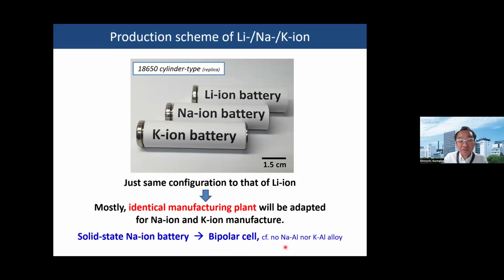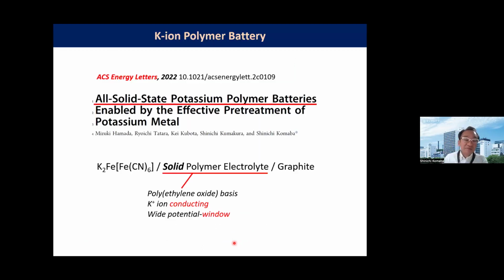And another point is there is no alloy formation between aluminum and sodium, or aluminum and potassium, so a bipolar cell can be made. Bipolar aluminum current collector can be applied, which is different from the lithium case, because in the lithium case, aluminum and copper foil should be stacked to avoid lithium aluminum alloy formation. And 2 years ago, we also reported all solid state potassium polymer batteries based on Prussian blue and graphite, sandwiching the solid polymer electrolyte based on polyethylene oxide polymer membrane.